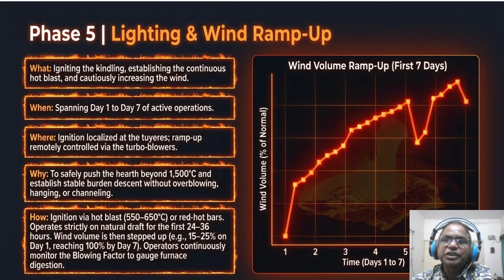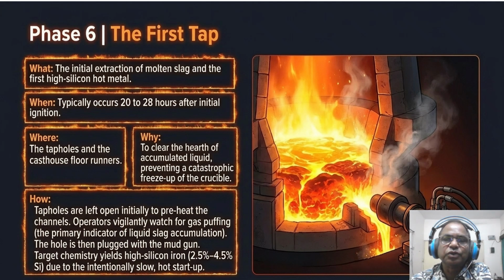Now coming to our transitional slide, which is after roughly 24 hours of successful ramp up, we reach the most celebrated milestone, and that is phase 6, the first tap. This visual captures the moment of truth. The first cast typically occurs 20 to 28 hours after ignition. You will see operators watching the tapholes for gas puffing. That rhythmic pulsation is the primary indicator that liquid slag has accumulated. Once we see that, the hole is plugged with a mud gun.